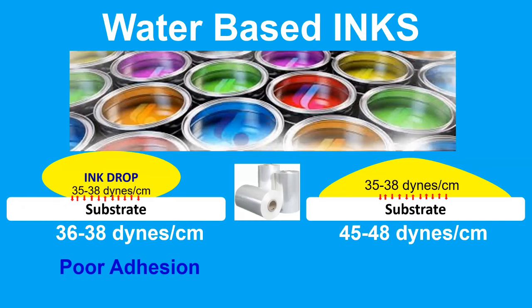On the other side, if our ink surface tension is 35 to 38 dynes per centimeter, and we are using a substrate with 45 to 48 dynes per centimeter, this will give us fantastic ink adhesion. So remember, the difference between the surface tension of inks and the surface energy of the substrate should be approximately 10